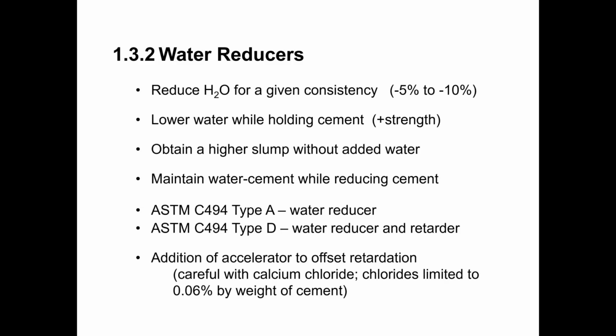Another reason to use a water reducer is to get more workability without adding more water. So we can use a water reducer and then enhance our workability of the concrete mix without having to actually add water and increase our water cement ratio. Another reason we would use a water reducer is to economize the mix by reducing the amount of cement. We can take cement out of the mix and maintain our water cement ratio by using a water reducer. So that way we are producing our concrete for a lower cost because we've removed some of one of our high cost materials, that being the cement.